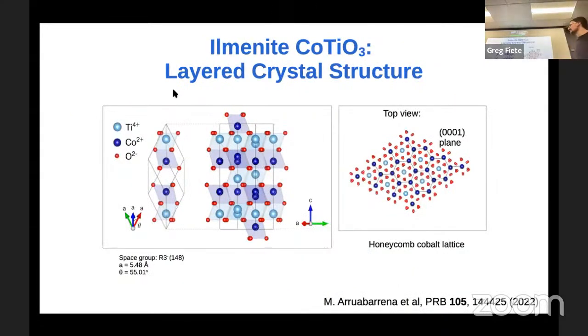Well, to present a little bit the compound, it's a layered compound. Ilmenite CTO has a hexagonal crystalline structure, which is organized in planes, titanium and cobalt planes, ordered along the hexagonal z-axis. They form octahedra, side-sharing octahedra between them.